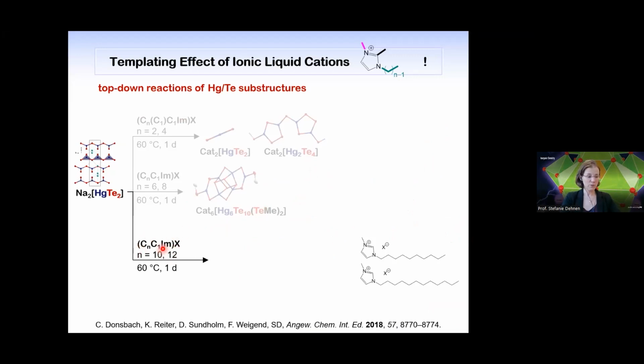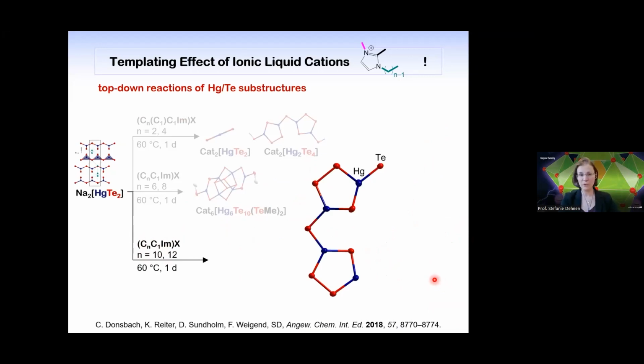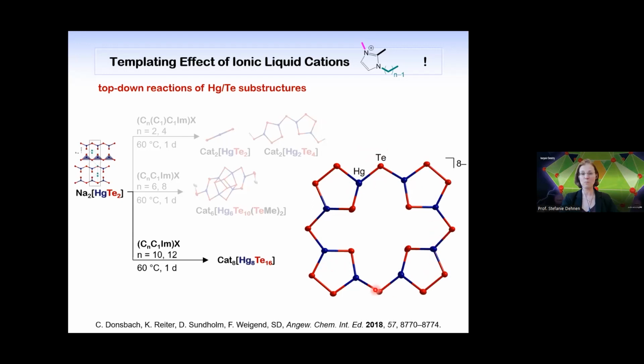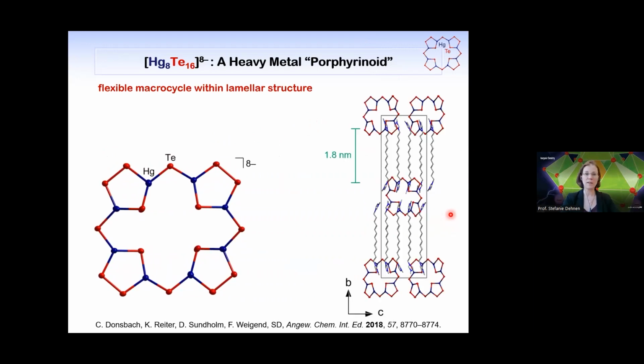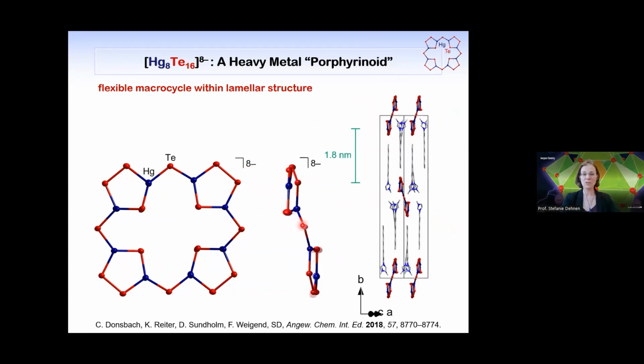Last but not least, we took decyl and dodecyl chains, and here you see the counter-ions, and what we got is this one. And this was, again, disappointing in the first moment, since you see that there is a structure relation with this trend here. And we thought, okay, so all templating effect is gone, and there is nothing to talk about. Yet when we grew the structure, we saw that it's actually not a strand, but a molecule. It's a discrete molecule with an 8- charge on it. And we find this situated within a lamellar structure. You see these long alkyl chains separating the anionic layers from each other, and eight imidazolium groups compensate for the 8- charge of this molecule. You see that the molecules are a little bit distorted, so they just fit within these imidazolium groups, and this is why this structure seems to be extremely stable.